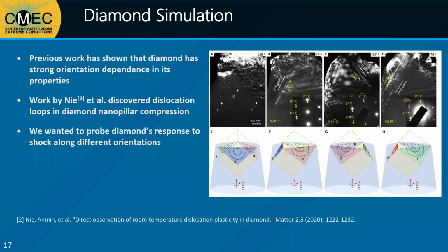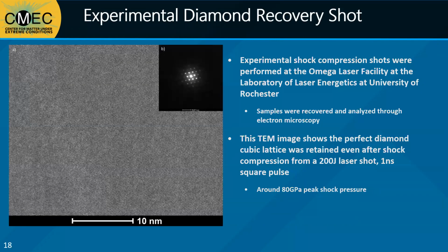To expand upon this, we wanted to probe how diamond would respond under different orientations when placed under dynamic shock compression as well. During a ride-along shot we had with Camellia Stan at the Omega Laser Facility at the Laboratory for Laser Energetics, we had the opportunity to perform several experimental shots on diamond with recovery. But unfortunately, at the time, we only had samples prepared for shock along the 001 direction.